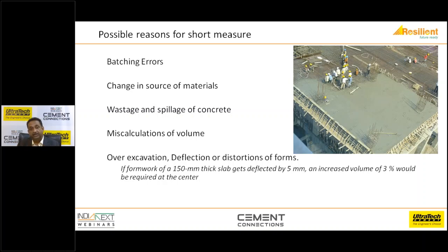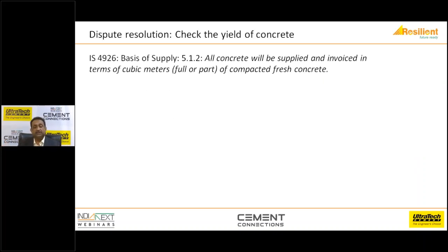Or if you have a foundation which is over excavated, or if you have a movement or deflection of the formwork, this can also contribute to a higher or lower volume of concrete being consumed. For example, if the formwork of a 150 millimeter thick slab is deflected by 5 millimeters at the center, you'll have a 3% increase in concrete. The way to check this is to check for the yield of the concrete. In your design mix, the RMC producer will tell you the total amount of batch weights, and that batch weight should give you what 1 cubic meter of concrete is designed for.